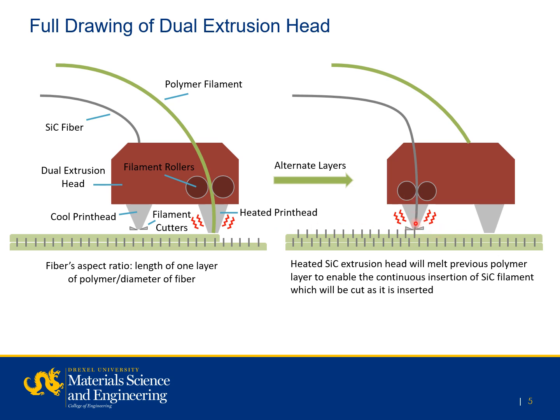same layer and insert these silicon carbide fibers with the heated head, which will continuously melt the previous layer and heat the silicon carbide fiber while continuously moving along the layer. It will insert the fiber, and as it is moving, it will cut with these scissors here the correct length so that these silicon carbide fibers are the same width as the polymer layer. This allows them to simultaneously be inserted into the first and second layer so that these will